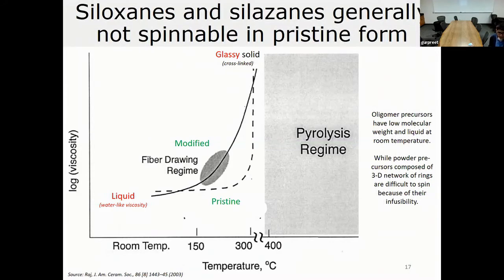One is to heat the pre-ceramic polymer to moderate temperatures, thereby inducing some cross-linking and viscosity changes. But when we tried doing that, what we observed is that this change in viscosity is rather dramatic. Nothing happens up to 100 and 150, and then all of a sudden around 250, 300, there is a rise in viscosity, and it just makes this transition from liquid to a glassy solid. There's insufficient time to draw fibers from this pre-ceramic polymer in pristine form. However, you can modify the chemistry of the pre-ceramic polymer, for example, by reaction with alkoxide, and that makes this change in viscosity more gradual. So that's one way.